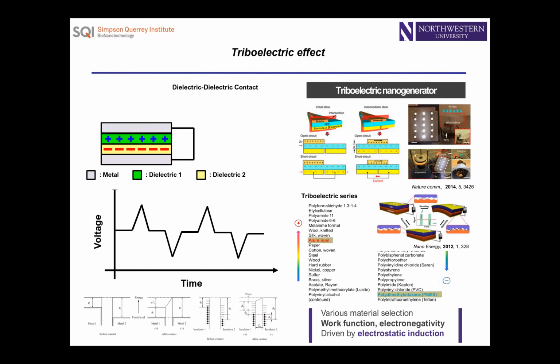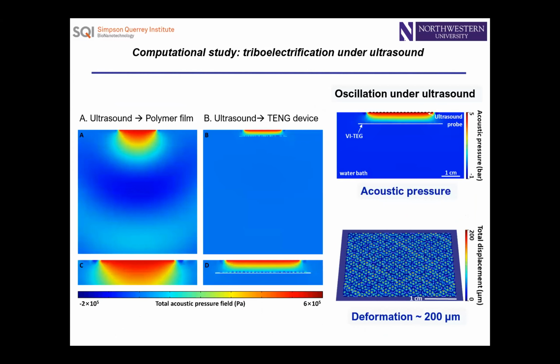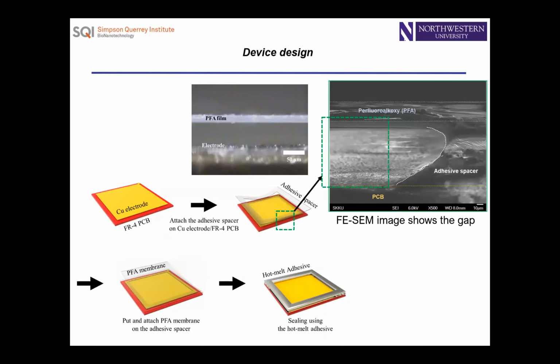So let me jump to the computational study. We went through a computational study to see what level of pressure and thereby deformation takes place under an ultrasonic environment. We found that with the layer structure, including the polymer and the metal electrode with a higher acoustic impedance, there's a chance to increase the acoustic pressure between the polymer and the metal. This will cause a level of deformation in the polymer, like 200 micrometers, which is not really significant, but it's pretty much feasible if we design our device to be less than that value. So based on this calculation, we designed our device with a displacement lower than 200 micrometers.